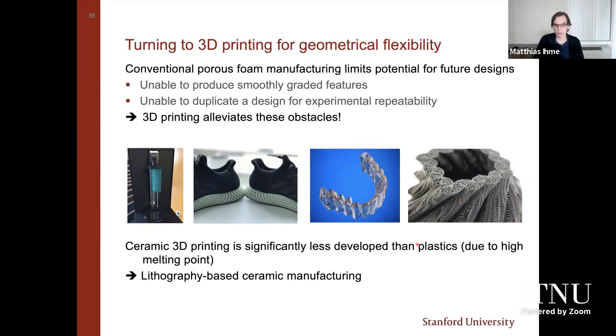What we are resorting to is a so-called lithography-based ceramic manufacturing system. And this works essentially in a slurry setup. I'll show you this in a second. This is one technology that allows us to print ceramic materials in a 3D fashion. And by using this LCM, lithography-based ceramic manufacturing, we have fairly good control over the accuracy of the pore structure in replicating the CAD drawing. And at the same time, we also have good control over the material properties of the ceramic structure.